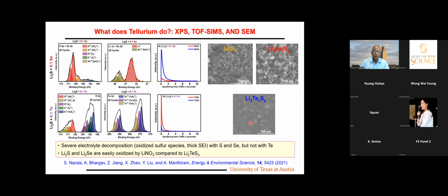So what happens when we add tellurium or selenium is they form polyselenosulfides, meaning selenium substitutes into the polysulfide molecules. In the case of tellurium, it does the same thing. It forms polytellurosulfide, and that migrates from the cathode to the anode side. At the anode side, it forms Li2TeS3, and that acts as a good artificial in situ created SEI layer, so that helps for the better cyclability of the cell in which we have added tellurium.